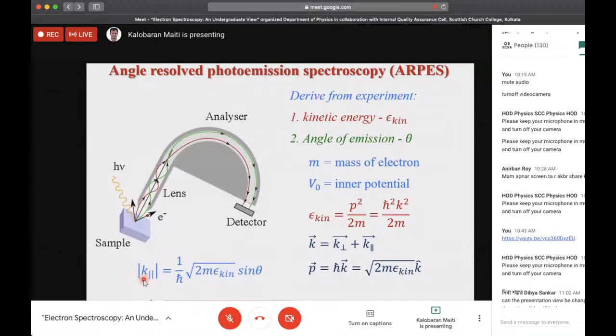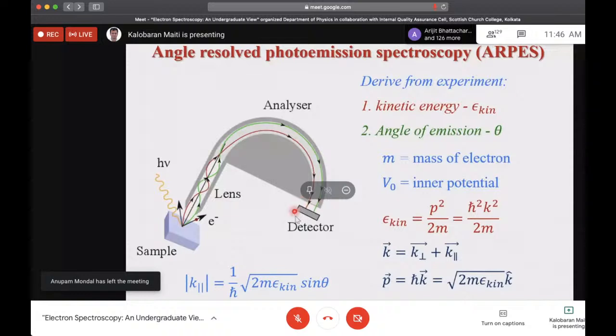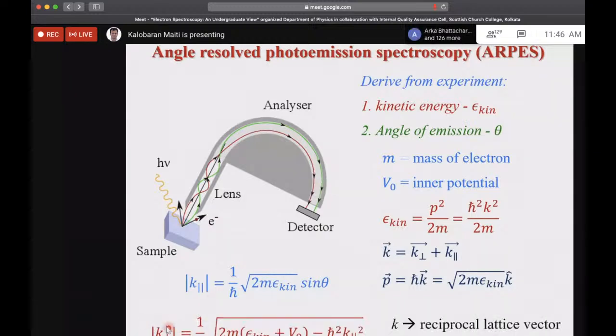So that means the electron that you have detected here, if you know at which angle it comes out, you can find out what was its K value before its excitation. So you know the binding energy, you know the K, so you can actually plot energy as a function of K, which is the energy band dispersion. Okay, so that's the way you find out the energy bands. That's the reason this technique is called ARPES, angle resolved photoemission spectroscopy.